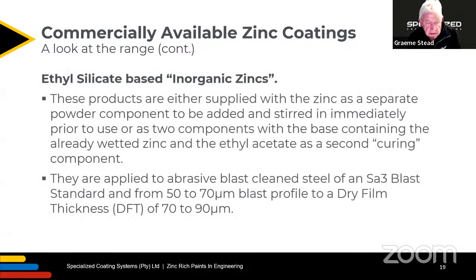These ethyl silicate-based inorganic zincs are either supplied with the zinc as a separate powder component to be added and stirred in immediately prior to use, or as two components with the base containing the already wetted zinc and the ethyl silicate as a second curing component. They are applied to abrasive blasted, clean steel of an SA3 blast standard and from 50 to 70 microns blast profile to a dry film thickness of 70 to 90 microns.